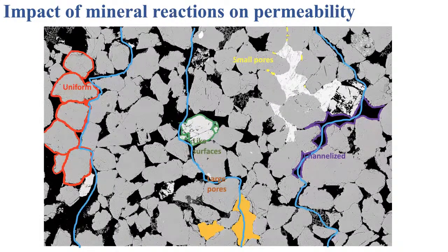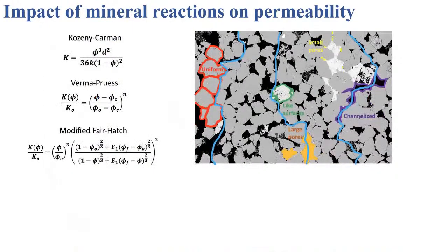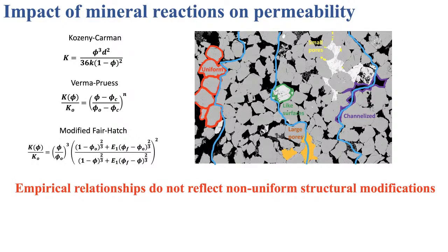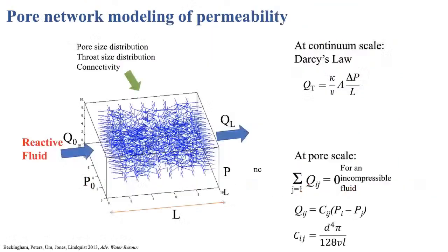The way we commonly estimate the evolution of permeability is using a continuum scale equation like the one shown here. The problem with these equations is that you get a single permeability for a given change in porosity. And so they're not able to reflect any non-uniform structural modifications that we have in our system. And so we need to account for changes at the pore scale. And we can do this with pore network modeling.